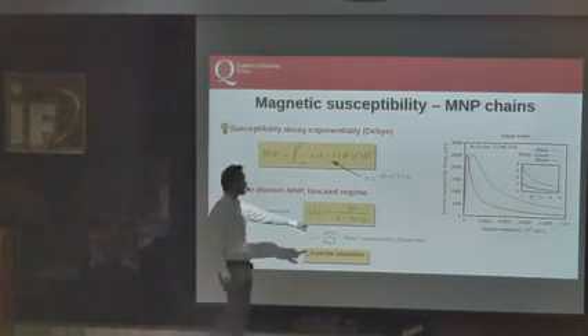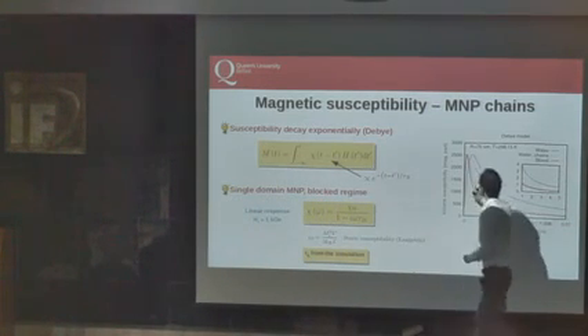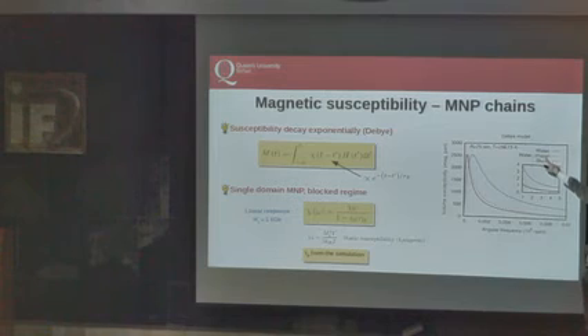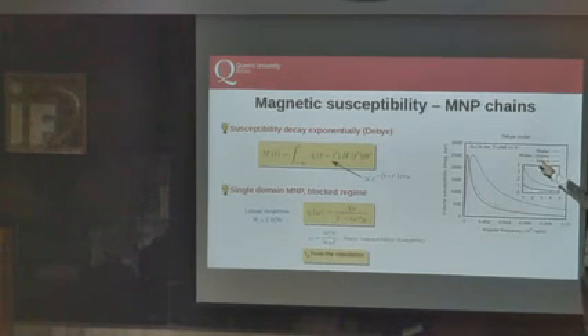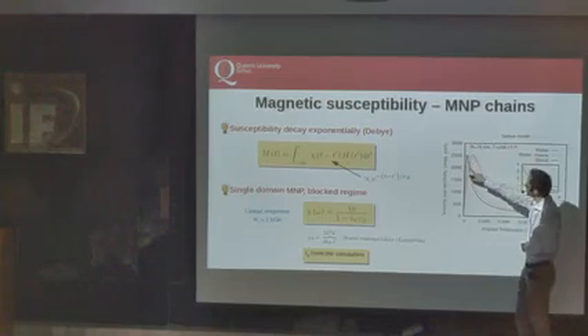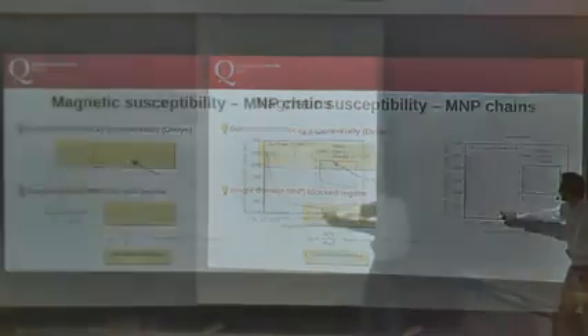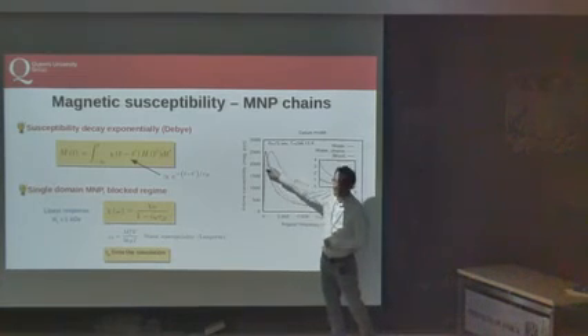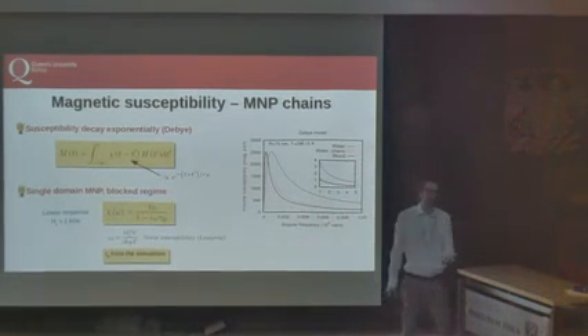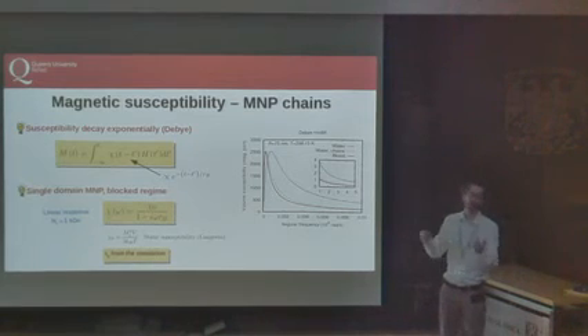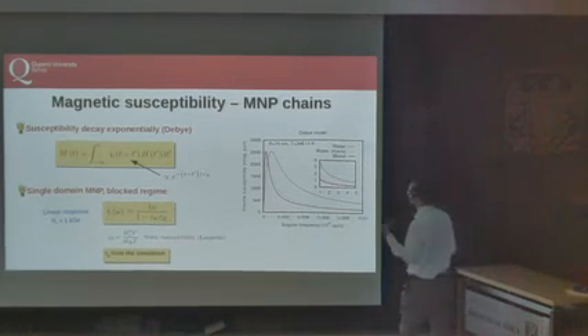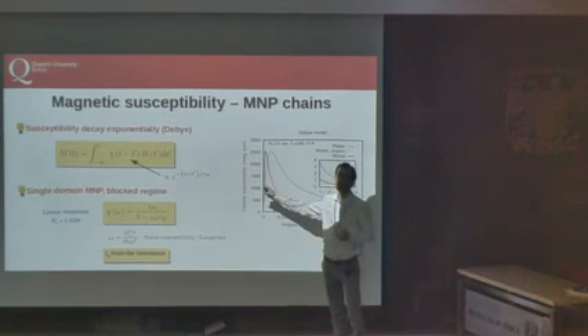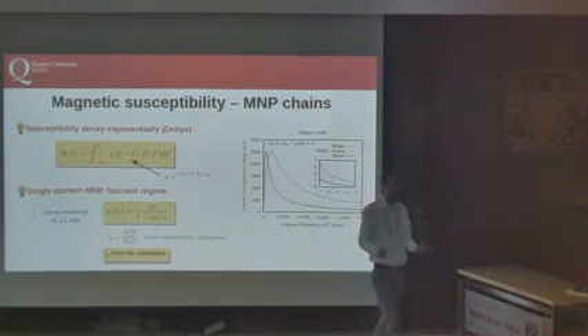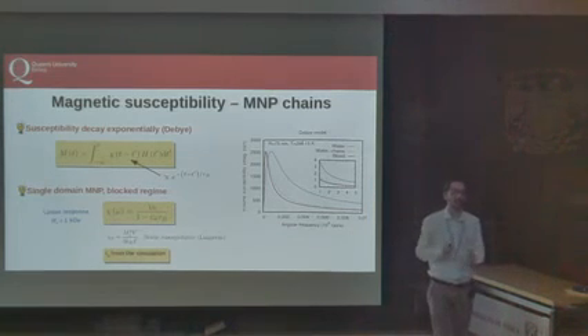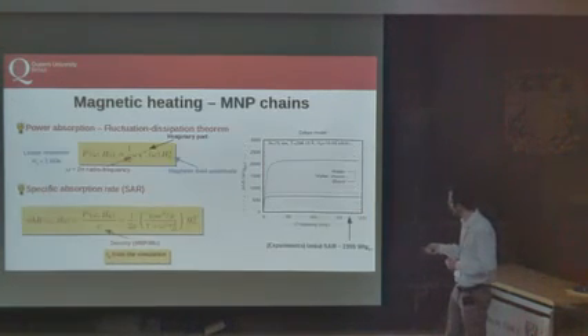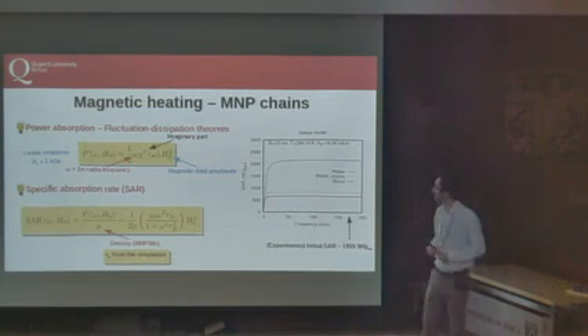If I plug the effective Brownian time in this formula, I see that the effect of having chains of nanoparticles in water is almost the same as having blood. So it means that, again, having larger objects formed by small nanoparticles, the average effect is to have a higher viscosity. They rotate with more difficulty. To finish up, what is the effect on the SAR?